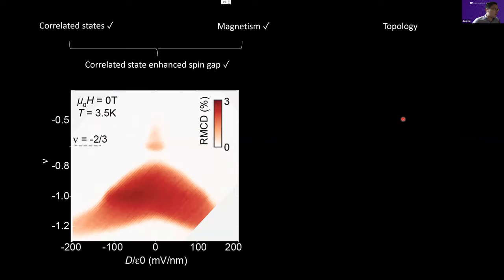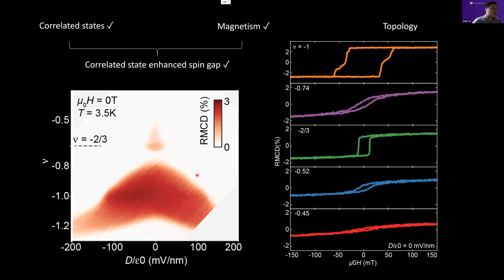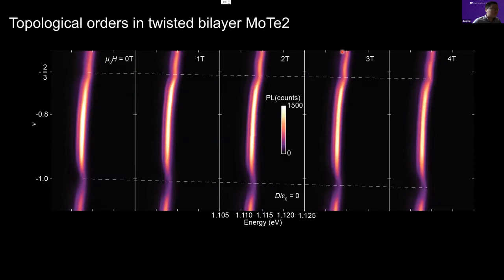We can now park our temperature at 3.5 Kelvin, and you can see clearly that the phase spaces of the fractional states and the integer state are separated. And by performing line cuts and magnetic field sweeps, you can see that in any other place they are soft magnets, but at the fractional states and integer states, they are hard magnets.